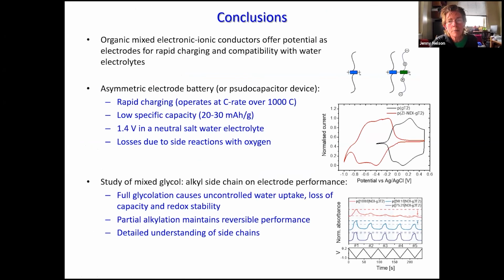So to conclude, I would first of all like to say that I think there's a lot of potential in using organic mixed electronic ionic conductors for electrochemical storage applications. We made a 2-terminal battery device and observed some interesting things. It can charge rapidly. It has a relatively low specific capacity, as you might expect for an organic semiconductor. It would work quite well in neutral salt water, but still has a loss of performance in the presence of molecular oxygen. We then did a detailed study on the effect of side chain structure on the performance of N-type and also P-type devices. And we found something quite interesting, which is that whilst full glycolation causes uncontrolled water uptake, a loss of capacity and electrochemical reversibility, a small degree of alkylation is able to maintain reversible performance.